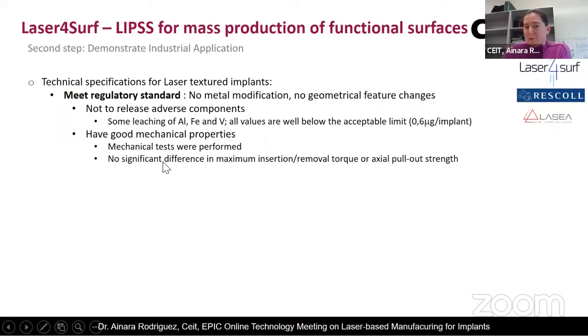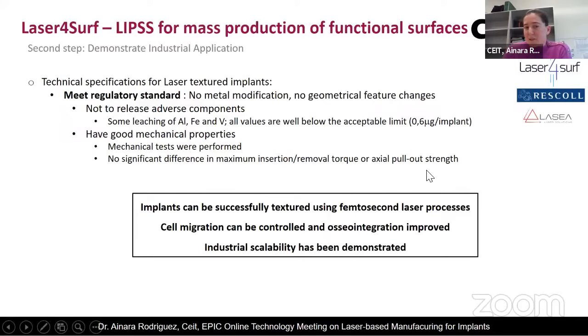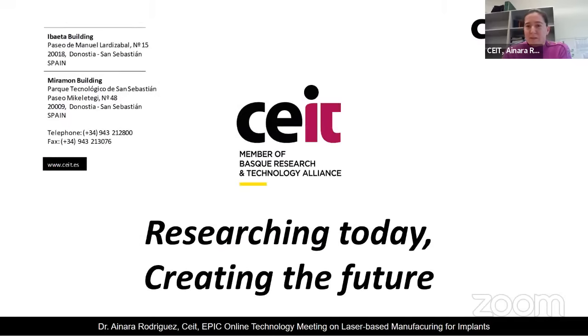And what about the mechanical properties? Well, similar results were obtained. We performed some mechanical tests on the screws in order to see if the mechanical properties were different from the original ones, and we saw no significant difference in the insertion or removal torque or the axial pull-out strength. So basically, implants can be successfully textured using femtosecond laser processes. Cell migration can be controlled and osseointegration improved. And also industrial scalability has been demonstrated. So this is a technique that is ready to be applicable at an industrial level. So this is all from my side. If you have any questions, I will be happy to answer.